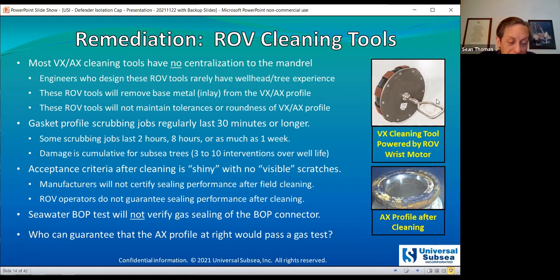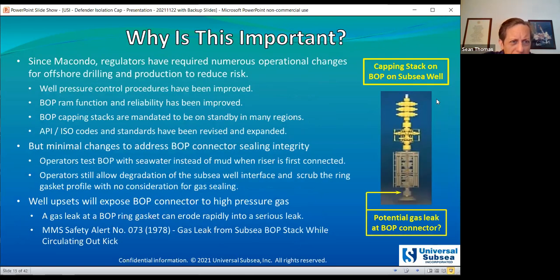And even more significant, we should mention that a seawater test will not verify gas sealing performance for this type of connection, particularly with the standard ring gaskets. And the gas sealing integrity is much more difficult to achieve than a drip tight liquid sealing. So, this exposes the industry to unnecessary risk, as opposed to the alternative of trying to minimize the degradation of the interfaces over the well life, which is what we're kind of getting into here.